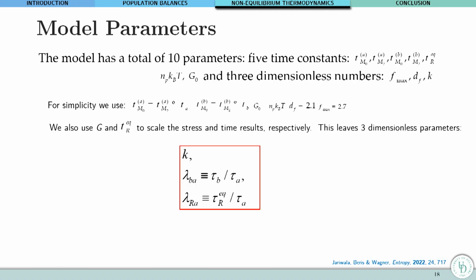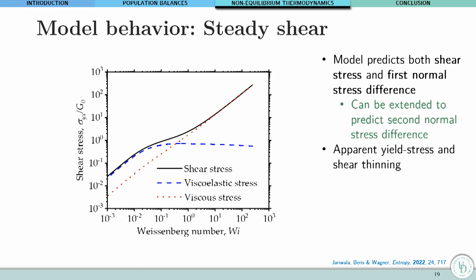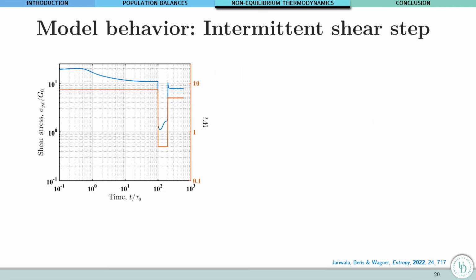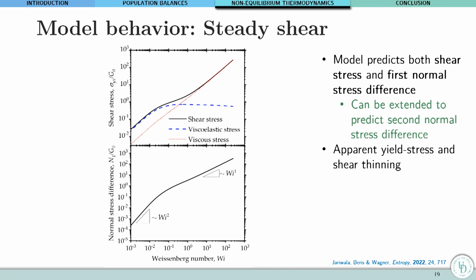But the fact is that there are calculations which you can go through and evaluate the final results. And then at the end, in the final results, many of the parameters now have physical meaning. We can make reasonable assumptions, end up with only 3 parameters to vary, this K and 2 characteristic time constants, and then end up describing thixotropic viscoelastic behavior as an apparent viscoplasticity, as you can see here, because we just wanted to show in this work a proof of concept,